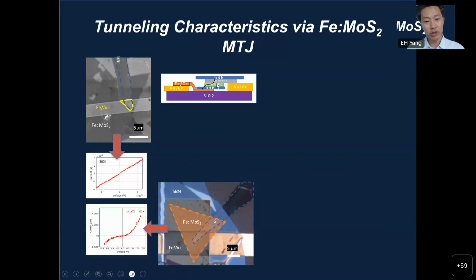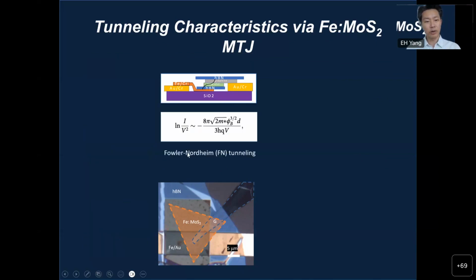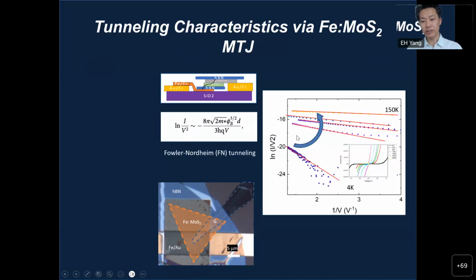So here we have hBN, we have graphite, the iron doped sulfide, and hBN. Then we have this iron, okay, layer that is a hard magnet, and then we have electrodes. So and then without the tunnel barrier hBN, we show this IV characteristic here that is linear. But then we put this hBN there, and this is a typical tunneling current. Okay, so tunneling current can be characterized by this Fowler-Nordheim tunneling, and that's exactly what we have per different temperatures.